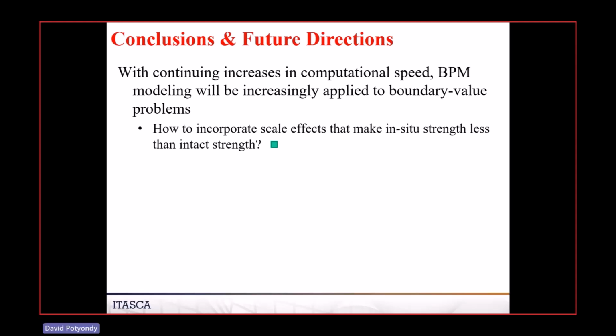That whole issue is not that well understood. There are some hypotheses I have, and I speculate on that in the paper and in that talk, but it's not 100% understood. So what people typically do, let's say we're doing another type of boundary value problem where we have a tunnel and high compression stress, and we know there's going to be some breakout notch forming in this material. What we might do is build a big, huge continuum model, and then in the region of interest where the damage wants to be explored, we put a PFC material in there.